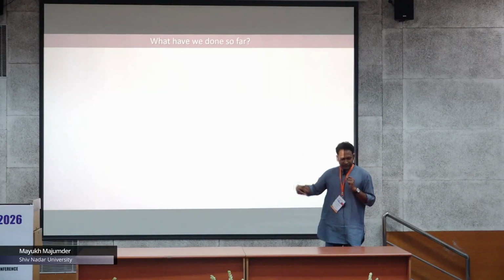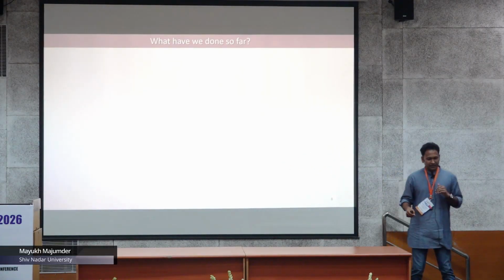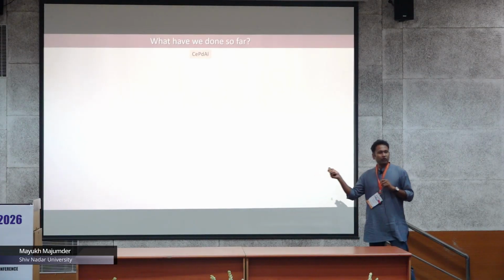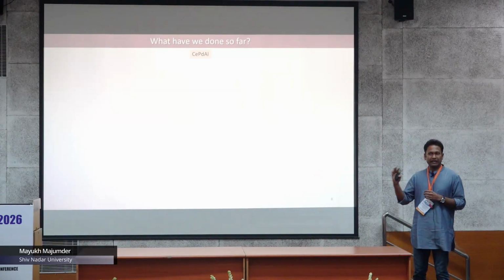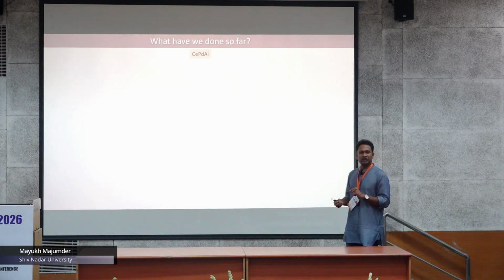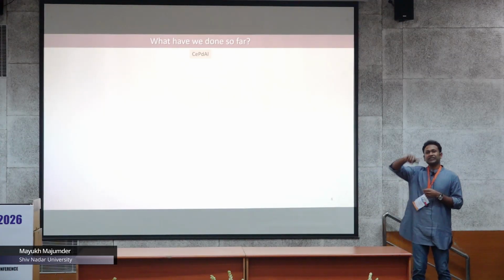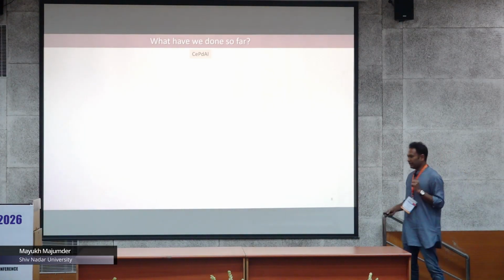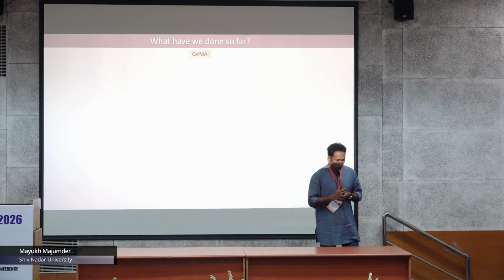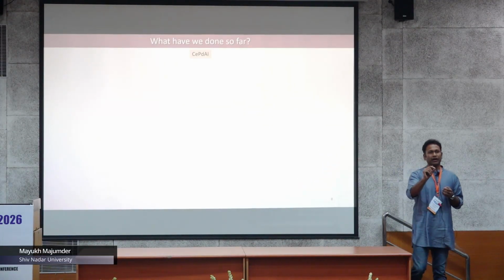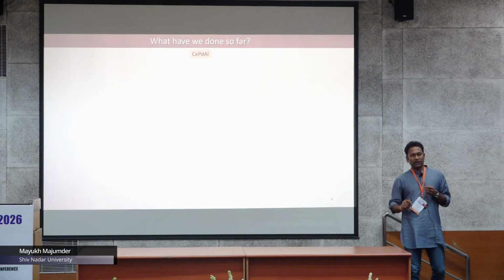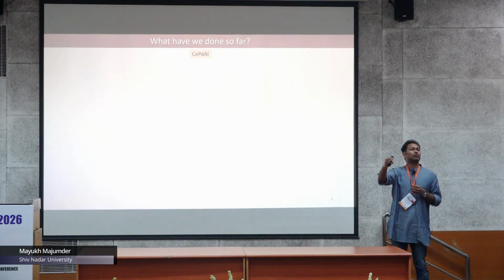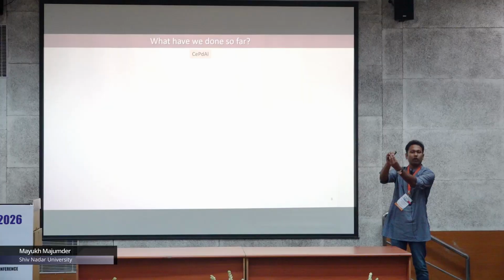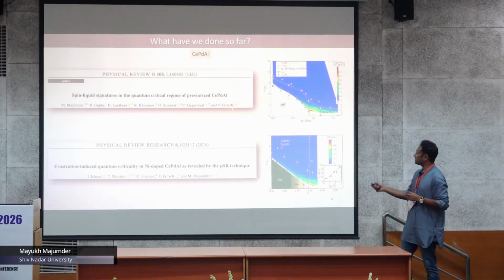Fine. So we have been thinking about these two problems that I have mentioned for the last, let's say, 4 or 5 years. We consider this particular interesting compound, cerium palladium aluminium, where the cerium moments are mainly responsible for the magnetism, and it is forming some sort of Kagome structure. It was already known that by the application of hydrostatic pressure or chemical pressure, you can suppress the long-range magnetic ordering and go to a quantum critical point.